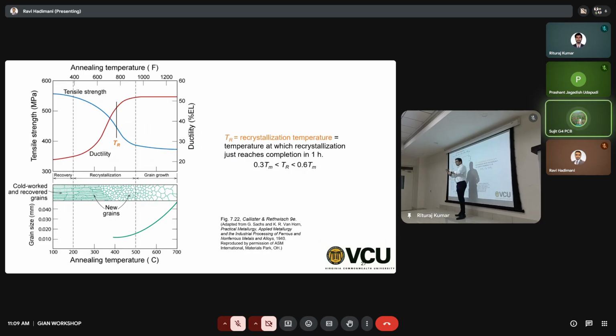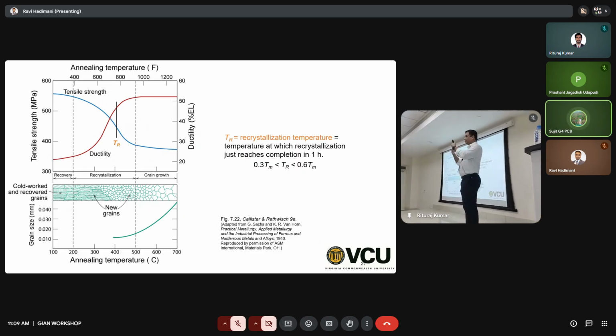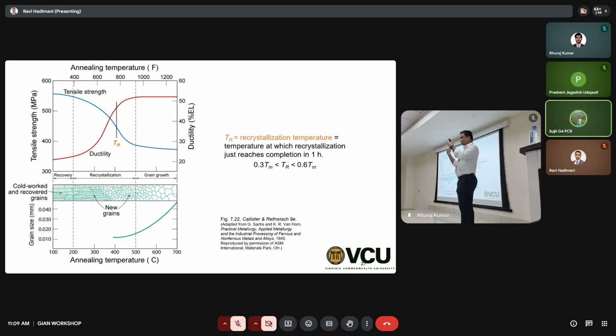Stress is relieved by moving the dislocations by doing thermal treatment, right? So dislocations can annihilate one another. Dislocations have directions. So when you increase the temperature, two dissimilar dislocations can come together and completely disappear. Okay? When you do that, you are decreasing the dislocation density. So when you decrease the dislocation density, you are basically increasing the slip length, which means you can increase the plastic deformation. Okay? So that is nothing but increasing the ductility.